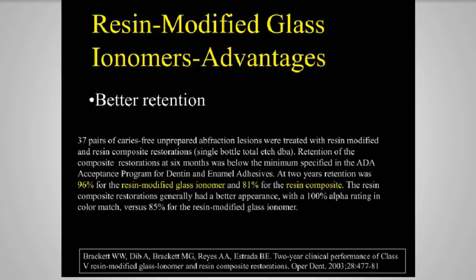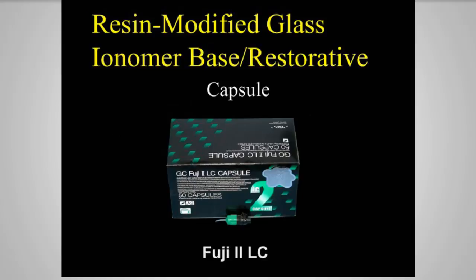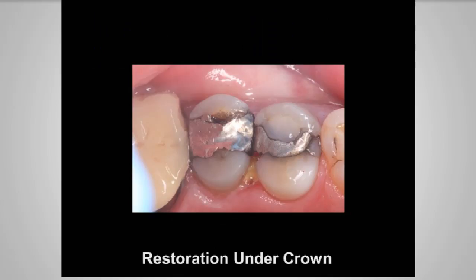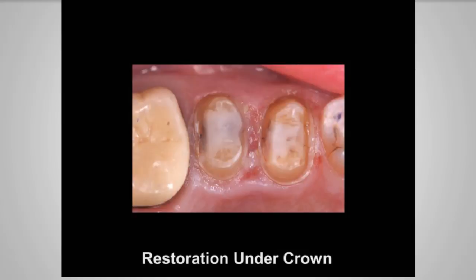Studies have shown that the resin-modified glass ionomers and the glass ionomers have excellent retention. And in this particular study, it was shown that resin-modified glass ionomer had a significantly higher retention in Class 5 restorations than do resin composites. Now, again, I work with a number of materials, but the one that I have the most experience with is your Fuji 2LC. And so I like to use these for restorations under crowns. Now, let me define for you when I like to use the resin-modified glass ionomer and when I like to use the pure glass ionomer.